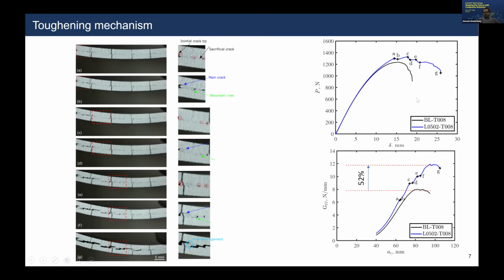So in this graph, we show the load-displacement curve for the baseline joint and a toughened bio-inspired joint, which is L0502, which means a joint with 2 millimeter crack width and 5 millimeter gap. The response is quite different between both joints. For the black one, which is the baseline, once the crack initiates, it propagates very fast without high dissipation. For the bio-inspired joint, the situation is different.